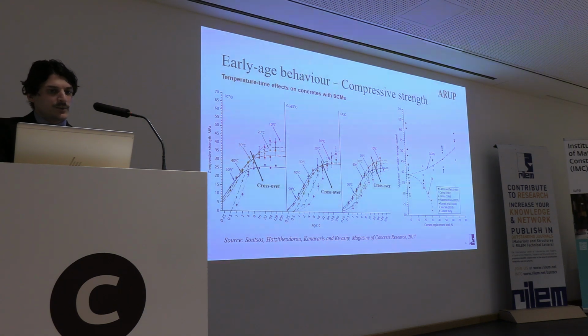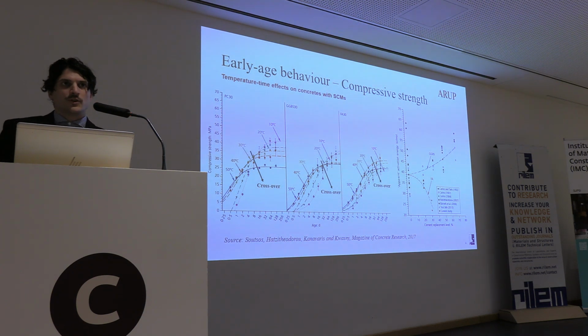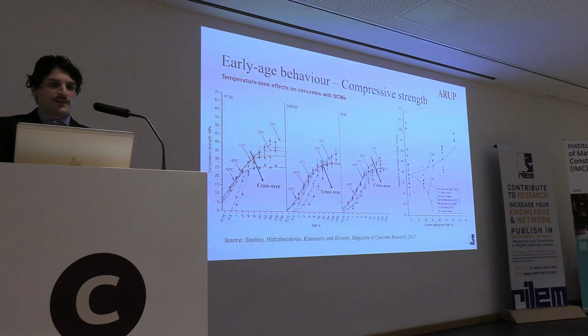And also identifying and trying to understand further the deleterious aspects of high early age temperature curing, such as the crossover effect, where there is a detrimental effect of a high early age curing temperature on long-term strengths, and how by using supplementary cementitious materials we can mitigate those and predict those more accurately with different models.